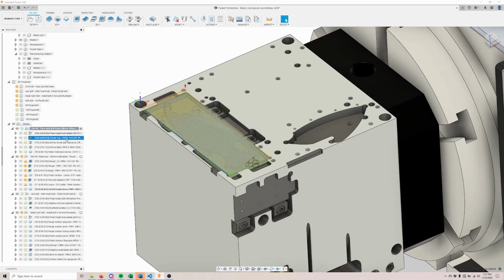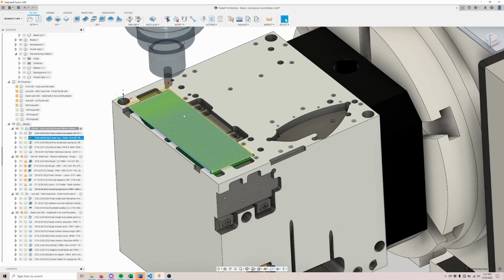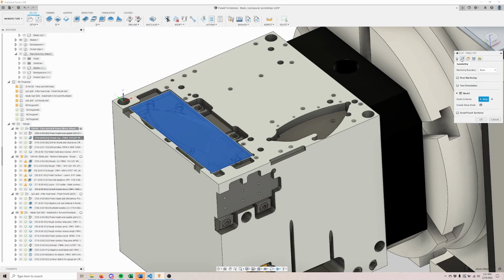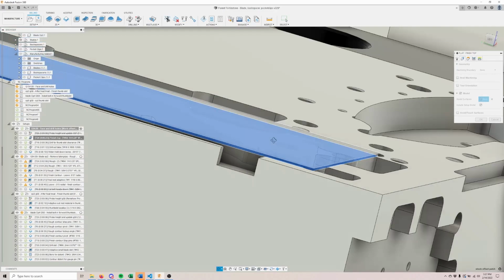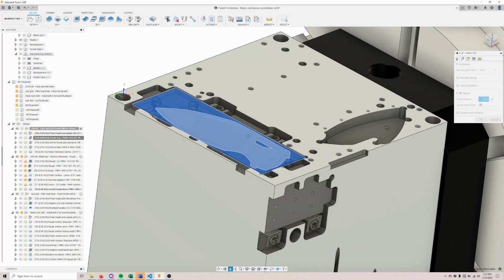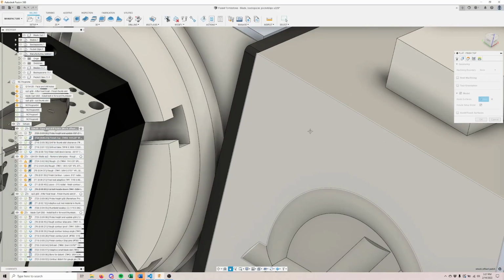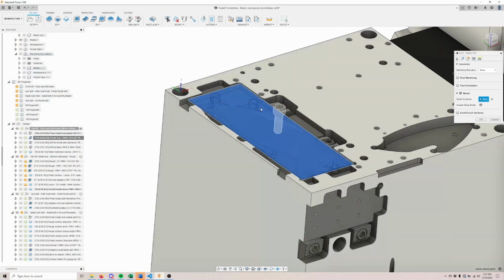So first we're using a flat toolpath, and I'm driving the depth of the flat toolpath using another body, which is located below the top surface. The reason I'm taking material off the top is because, after heat treat, we're going to surface grind, and I don't want to have to surface grind whatever 5/32 is all the way down to 0.125, because that would take all year. So we're essentially facing the part down to a dimension that's closer to 125. I think it ends up being like 133 or 132, which is pretty repeatable.